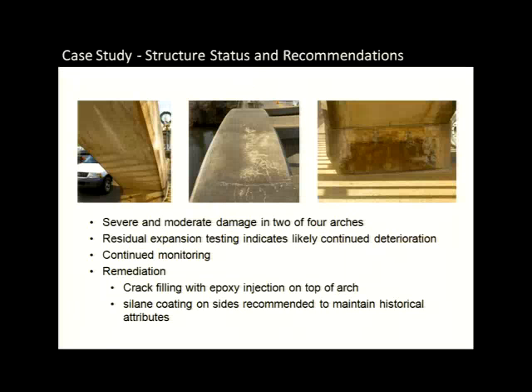Just a few nice close-up pictures of the bridge. We've been monitoring this continually for the past 5 years. What they're actually going to go in and do in the springtime of next year is do some epoxy injection on the cracks from the top surface of the arches so that they can fill those cracks, bridge them, and try to prevent any additional moisture from coming in. And then they'll come back with the silane and coat the exterior surfaces of the concrete to try and dry the structure out. Two of my colleagues from the University of Texas actually were just in Alabama this past week, and they instrumented the arches with 48 relative humidity probes inside the concrete so that they can monitor how effective these different mitigation techniques are at really reducing that internal relative humidity.